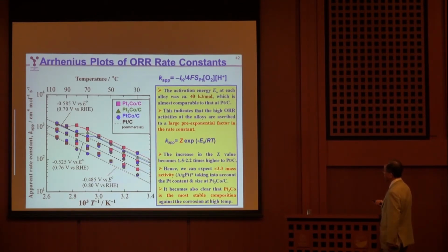But this composition is most active and most stable, at least until 80 degrees Celsius. So by this nano-size experiment, we could confirm the alloy catalyst shows superior catalytic activity compared to the bulk platinum. But the problem is still that the stability is not enough. So we are now working on stabilizing the skin layers much more, using electrochemical annealing or some chemical annealing process, a new method. And now the stable region is expanded to 110 degrees Celsius. Not shown here now, but we believe that we have almost reached practical catalyst preparation.